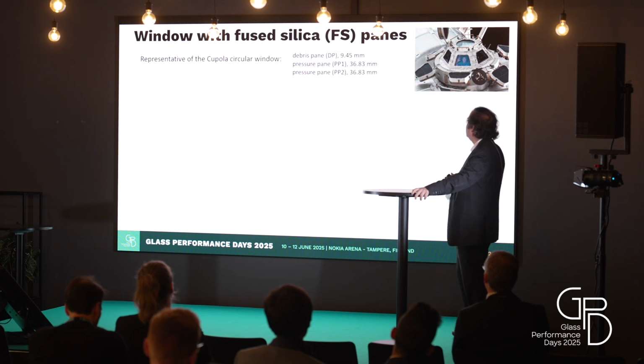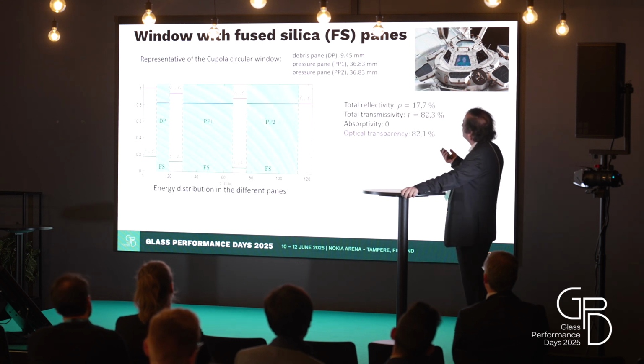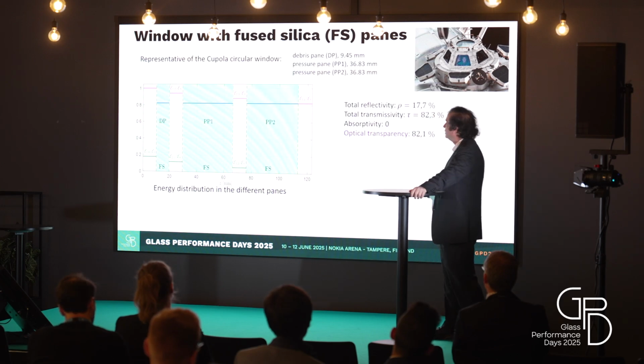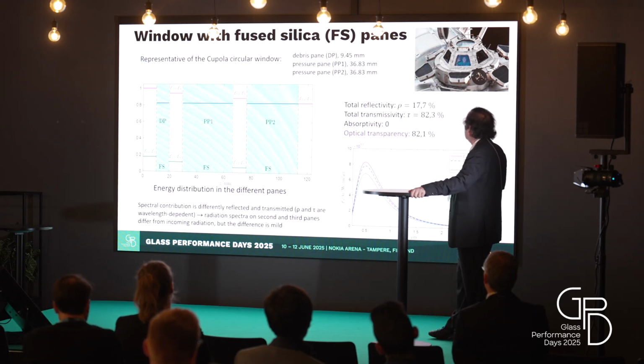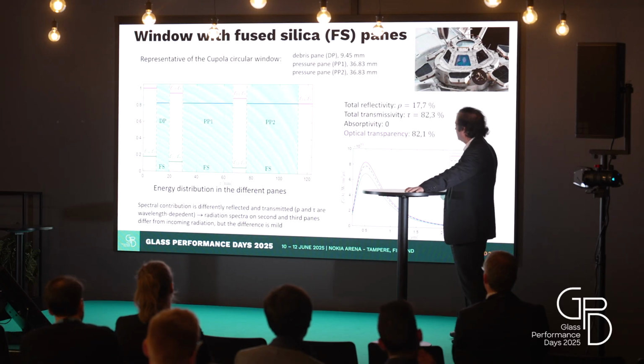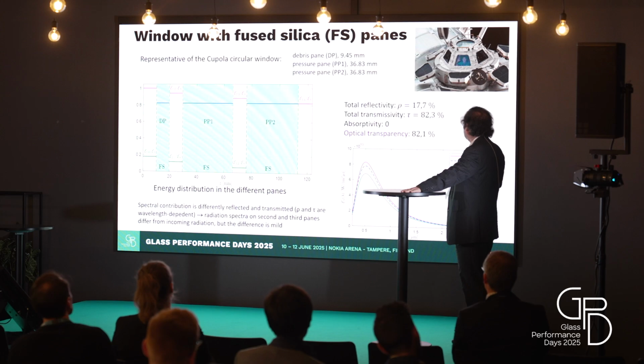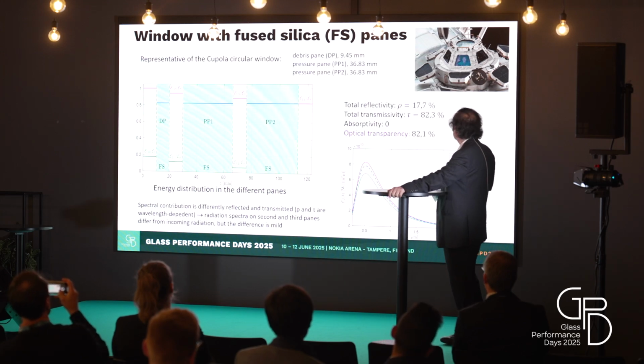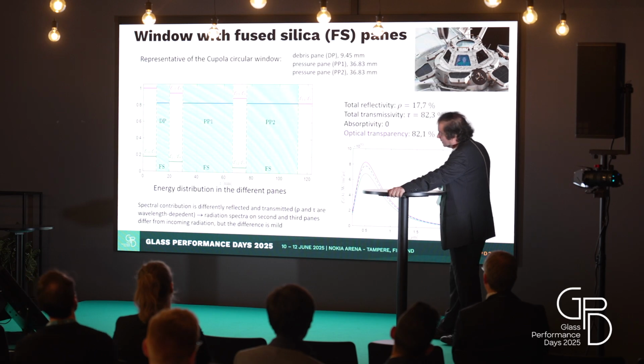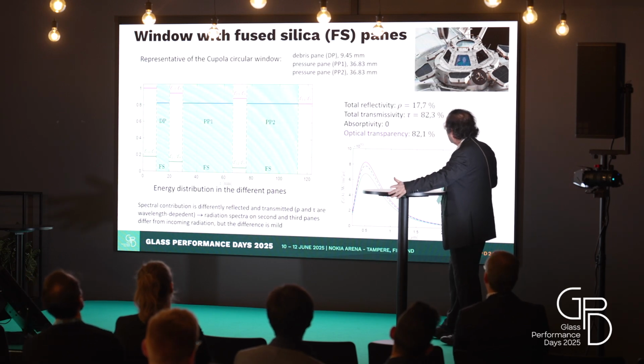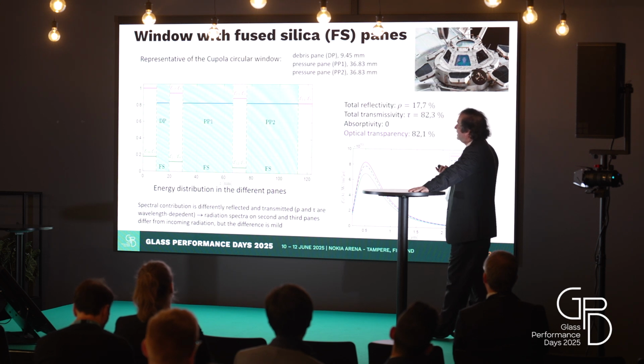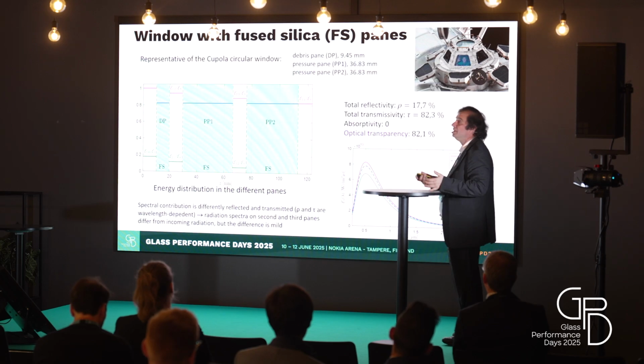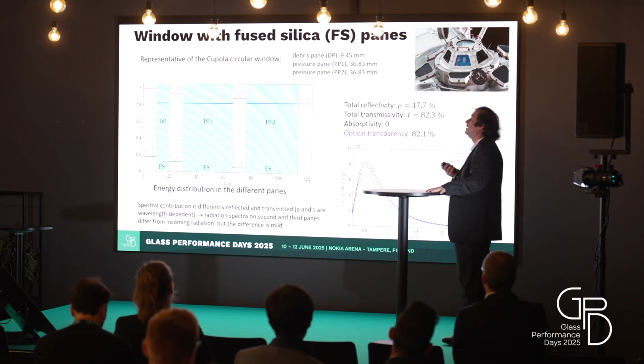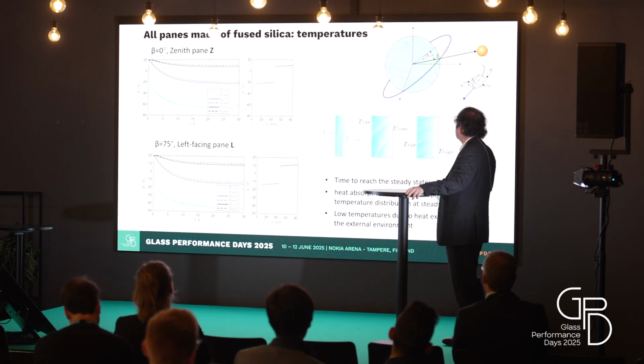So I will just present an example in which I consider the same package of the International Space Station. You can see that you have an energy distribution that varies a little bit depending on the wavelength because of the limited absorption of fused silica. But since it is almost transparent, you don't have a very strong dependence on the thickness, so the properties of the windows are only mildly affected by the thickness. And the temperature that you can reach